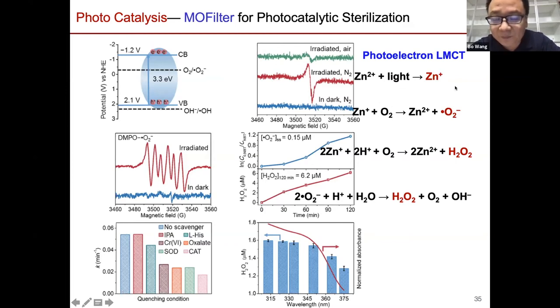Eventually oxygen gets another electron from Zn+ and stabilizes the whole structure. You get a superoxide that way. And we confirmed the result using the capturing agent DMPO to confirm the superoxide generation here. We also analyzed superoxide over time, from 0 all the way to 2 hours, and you can see the superoxide radicals generating gradually. And as we all know, superoxide lifetime is rather short. It will either react with oxygen to give you hydrogen peroxide, or it will further react with water to give you hydrogen peroxide. So hydrogen peroxide is accumulating in these cases. As long as you shine a light on ZIF-8, it will give you hydrogen peroxide gradually.